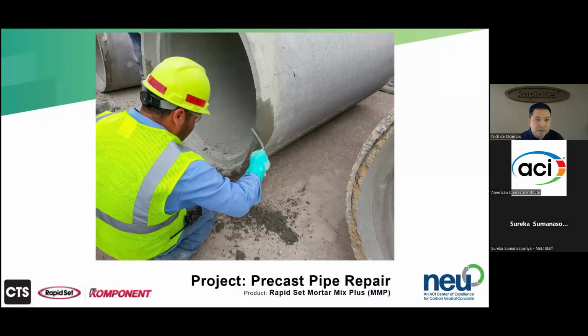Getting away from the more beautiful things, this is some precast pipe repair - also beautiful, just a different kind. This is Rapid Set Mortar Mix Plus being used, basically troweled on. Notice this piece of pipe that was damaged here - they're repairing it. Rather than having to toss or replace the pipe, we can come in with Mortar Mix Plus, trowel it on, get the necessary finish that will harden and achieve 3000 psi in a few hours, ensuring a very fast repair and the smooth surface required for these pipes to fit and function properly when placed.